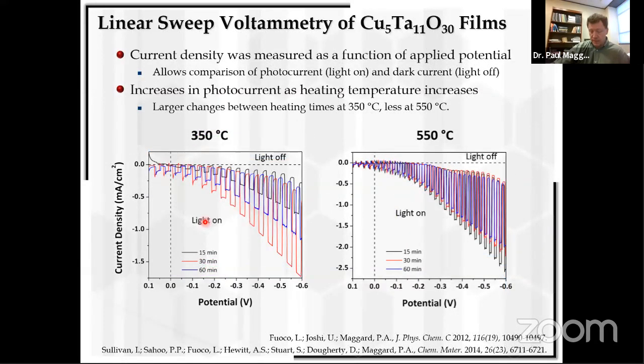Again, you set these up as films, you irradiate them in an electrolyte solution, and you measure the photocurrents. Here I've shown you two plots. One where we've taken the film, annealed it, and then heated it to 350 to oxidize it some, or we've taken that same film and heated it to 550 to oxidize it some. And we swept the potential under chopped light. As you see this curve going to the right here, we're sweeping the applied bias of that film negative, and we're chopping the light on and off.